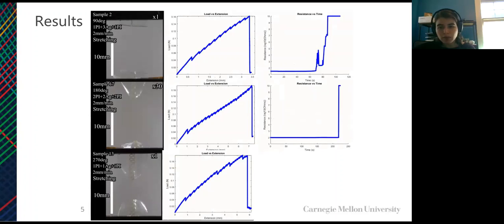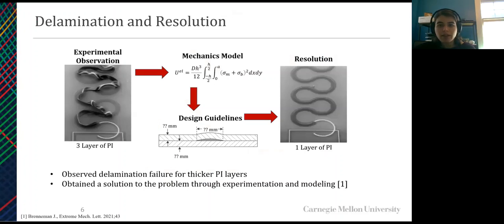The parameter we are mostly interested in is the strain of failure, which varies depending on the angle of curvature. The 270-degree angle of curvature had no initial connectivity prior to being tested, so the resistance plot is excluded here. The varied thickness of polyimide and silver layers was also investigated, but did not have a significant effect on the strain of failure characteristics of the interconnect.